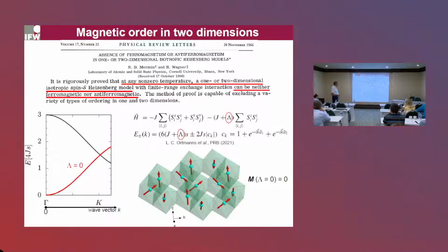And if one calculates the excitation energy spectrum of this kind of system, then one can obtain the dispersion relation between the energy of the excitation and the wave vector. And one sees that for long wave excitations, characterized by a very small wave vector k, the energy needed to excite a spin wave is infinitely small. That means the two-dimensional layer cannot have a long-range order, and the spins will fluctuate in different directions when the system is truly isotropic.